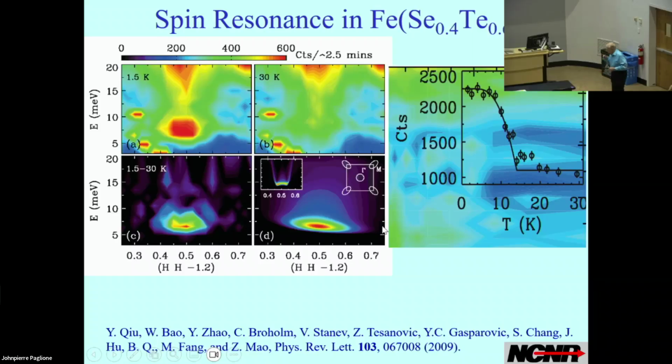Okay. And then we've had some beautiful lectures on the order parameter for the superconductivity, D wave, and a D wave will give you a special spin resonance in the excitation spectrum. And that proves that the system is unconventional. Iron superconductor is the same idea. So this is energy, and you see this new excitation come in. The intensity of that just follows